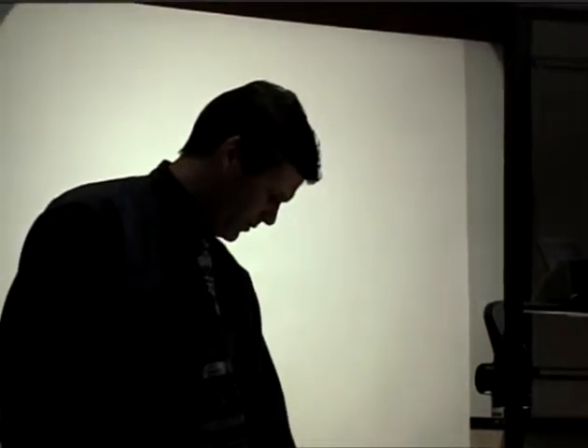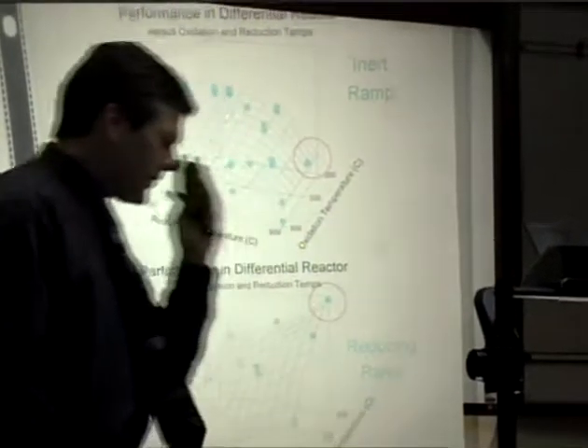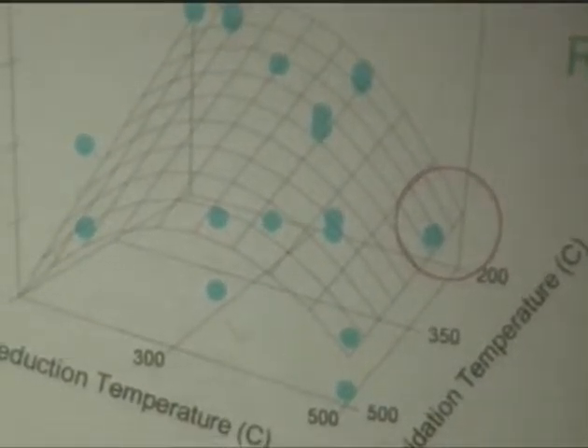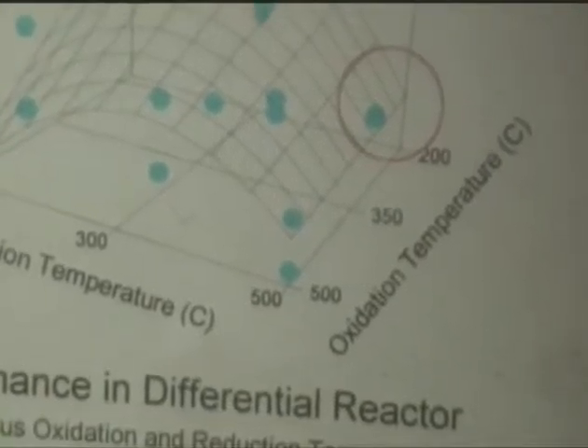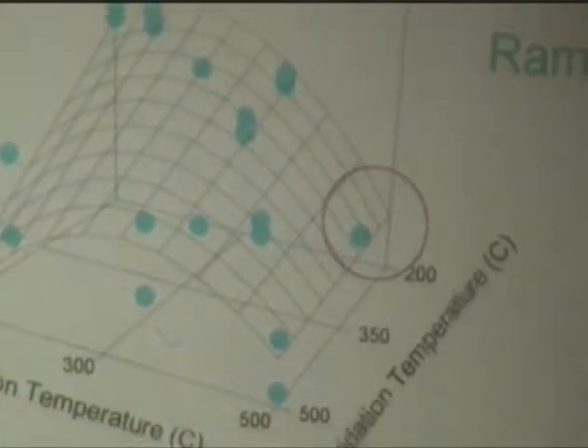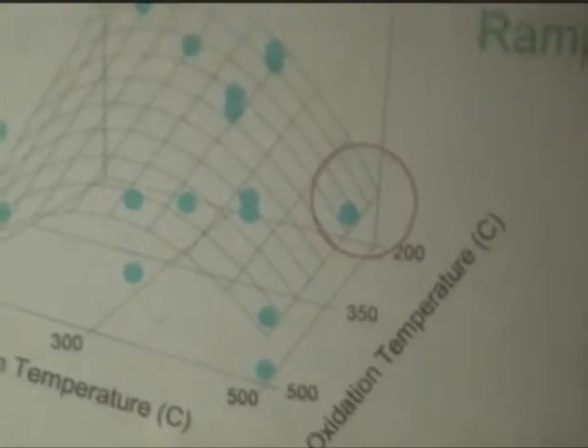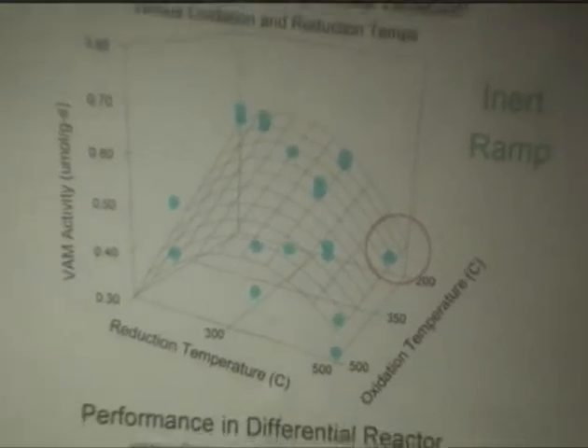So again, very simple. Either we ramp the temperature in an inert or we ramp it in a reducing atmosphere. And what we found was very interesting. First of all, it might take some time to get used to these structures, but essentially it's just a three-dimensional plot where we plotted the reduction temperature here on the x-axis, oxidation on y, and then z gives you a feel for the activity. Okay.